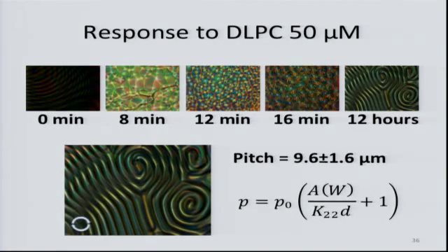But here, for example, what I know, I'm not talking right now about chirality. Here you have a cholesteric liquid crystal in contact with a particular surface active molecule, which in this case is a phospholipid, but it can be just a regular one-tailed surface active molecule like a soap surfactant, and it will produce these changes in texture towards this fingerprint texture.